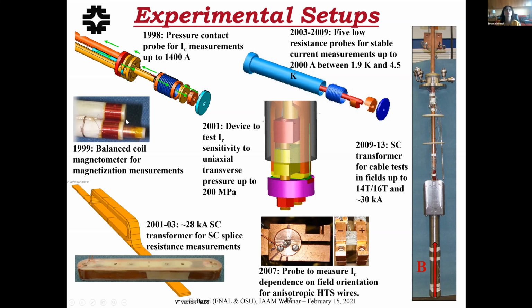Then we designed this very simple balance coil magnetometer to measure hysteretic curves of these materials. This is a very cheap probe made of G10, but you can also buy much more expensive vibrating systems for this. But we had limited resources, so we tried to do our best. This is a device that we designed a long time ago to measure the effect of transverse load on the Rutherford cable itself. So we apply a pressure with a hydraulic cylinder, and then we measure the critical current performance on a single wire, so we didn't need to use huge power supplies.